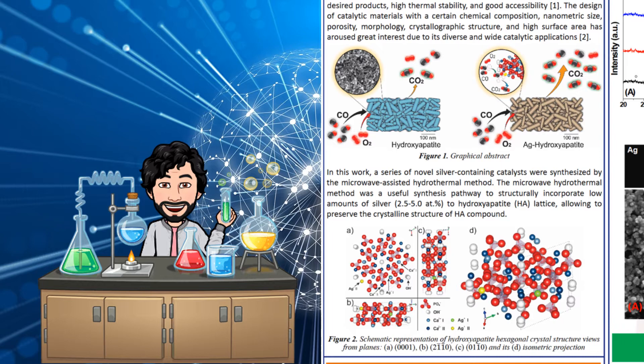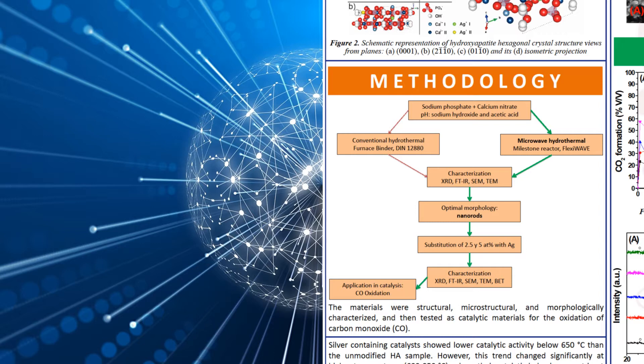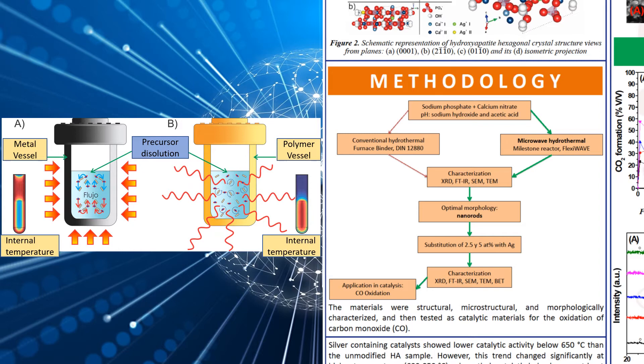The methodology is described below. The materials were prepared using calcium nitrate, sodium phosphate, sodium hydroxide, and acetic acid. The ceramics were synthesized by the conventional and microwave-assisted hydrothermal method.